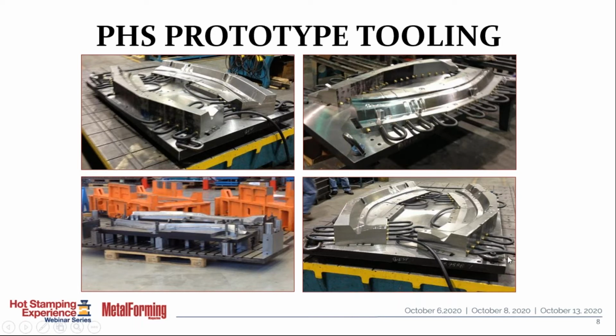The purpose of the cooling is to cool the die down to a temperature that is low enough to be able to absorb all of the thermal energy from the blank as it quenches, so that you exceed that 27 C per second rate that was mentioned earlier. And that gives you a relatively trouble-free transition from austenite to martensite without any chance of having retained bainite. And so you can do that with a room temperature tool.